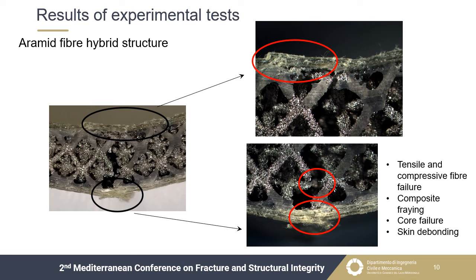The fracture surface of the carbon laminate was sharp and clean, while for the aramid a kind of fraying of the fibers was observed. Moreover, for the aramid skin structure, a partial failure of the core was observed. These different damaging features can explain the different shape of the loading curve, characterized by a decrease of the rigidity near the maximum load.